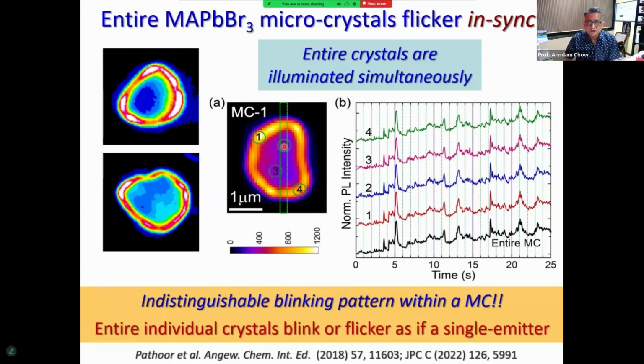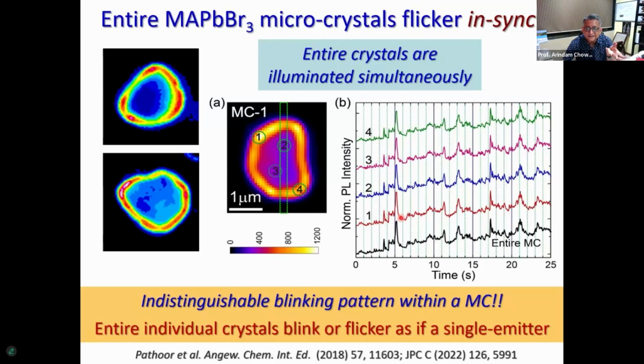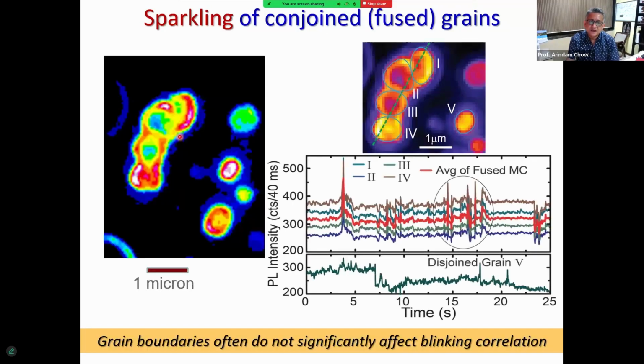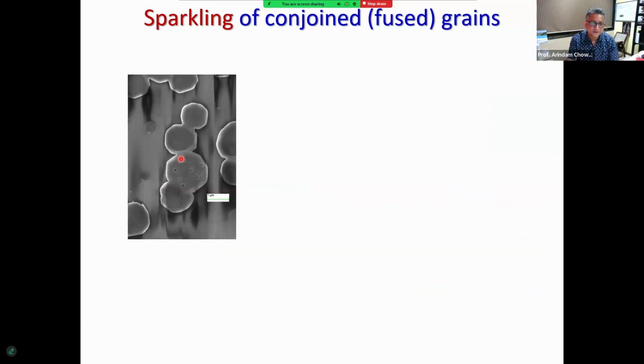As you can see, if I look at positions 1 to 2 to 3 to 4, which are almost 1 micron away from each other, and plot the emission intensity as a function of time, I see that the peaks and valleys and the jumps all come together. So it was very bizarre and intriguing at that point of time, because it seemed that these entire crystals were blinking or flickering as if they are single nanocrystals or single quantum dots. However, there is absolutely no quantum confinement in these systems. If you shift to crystals which had conjoined or fused grains, as you may have seen in the SEM picture before, you can see that as they're growing, they can get connected and fused. We thought that in these, this kind of behavior should not happen, but this is what we found out. Of course, this is a different grain, not the one shown in SEM.